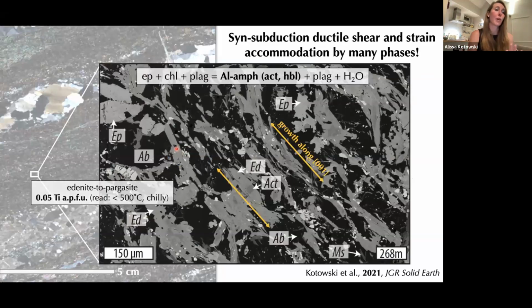And we can see this if we look even closer with a backscattered electron image as well. So you can see these amphibole porphyroblasts here with cores of actinolite and rims of edenite and pargasite. And these rims are growing parallel to the lineation within the foliation here along the amphibole 001 direction. They're also surrounded by lots of albite, some chlorite and muscovite, epidote. And if you speak amphibole, this zoning with actinolite cores to edenite rims actually means that these minerals are growing as this foliation is deforming, as pressures and temperatures are increasing. So this zoning is telling us that this fabric is prograde, forming during subduction to peak conditions.